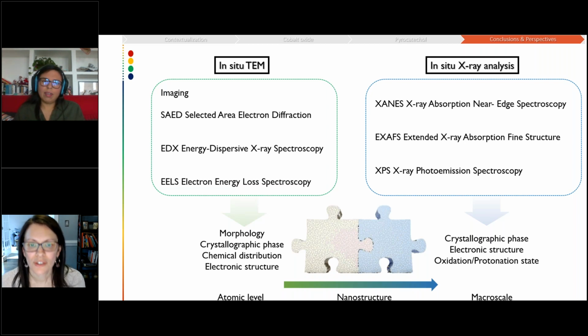Great. Let's do one more, since we're a little over time, and then we'll get you connected with everybody to answer the rest. Really nice work. In the electrolyte comparison slide, maybe slide 19, did you do any quantification of the cobalt in solution afterwards? Structural changes might indicate dissolution, and counterions such as chloride and sulfate could have significant impacts on the resulting structures after cycling.